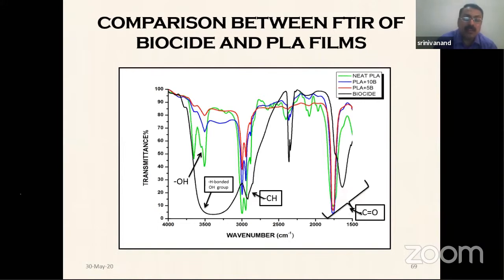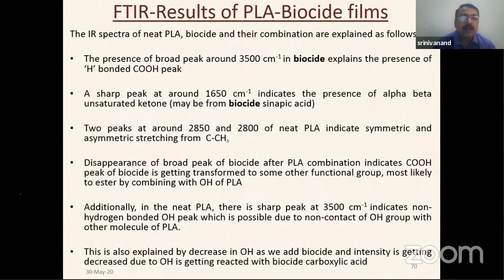So what happens here is the neat biocide, that is biocide itself, is capable of forming hydrogen bonds, which is indicated by a broad peak. So when the biocide is incorporated with PLA, the hydrogen bonding peak is getting decreased. So the decrease in the hydrogen bonding peak is the indication of the biocide having interaction with the PLA. And based on that, we found the following observations.